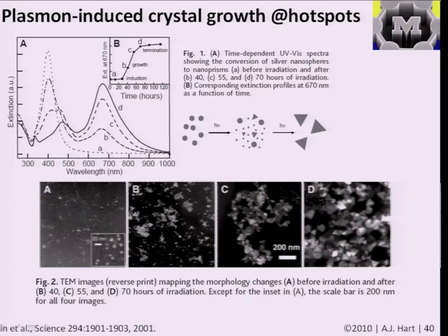And so these are pictures from a paper from Chad Mirkin's group at Northwestern about 10 years ago, and they worked on a synthesis of nanoparticles in solution. They were looking at how to make silver nanoparticles by taking a salt dispersed in a liquid and learning how to change the conditions, the temperature, and so on, to produce particles of certain size. And this all happened completely by accident, unexpectedly, because they basically left their solution, which they hadn't done their process on yet, out in the lab in the fluorescent light over the weekend. And they observed that when they came back on Monday, this is a true story, it was a different color.